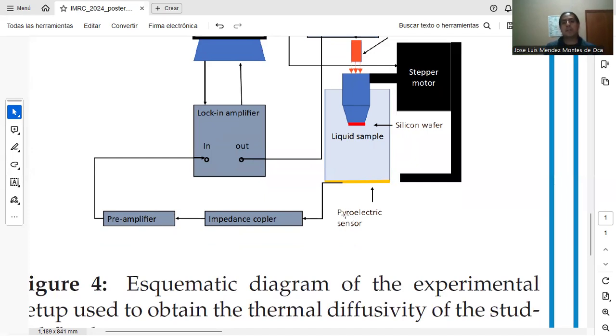And usually this signal obtained is low in amplitude and has some noise, so it is pre-amplified and sent again to the lock-in amplifier. And the lock-in amplifier makes an operation between the measured signal and the reference signal, obtaining a clean signal with a well-defined amplitude and phase. And well, in this case, the phase is the difference in phase between the measured signal and the original generated signal, the reference signal.